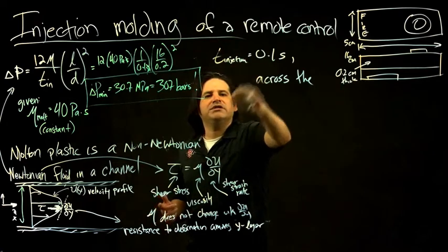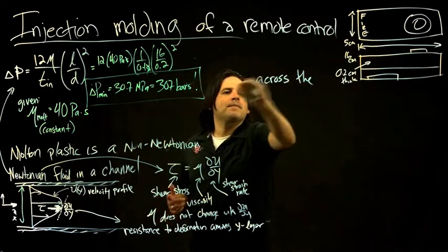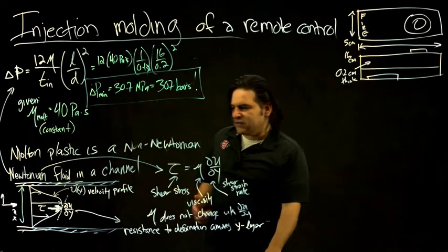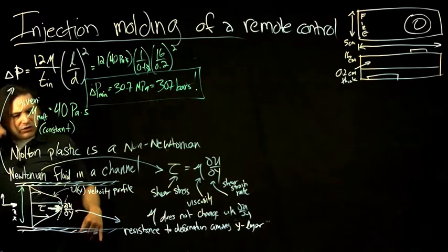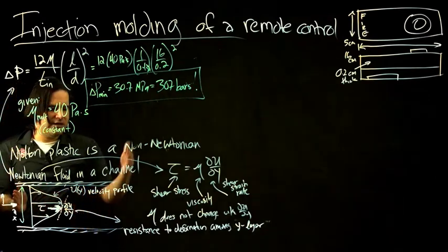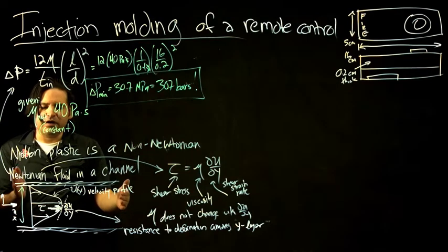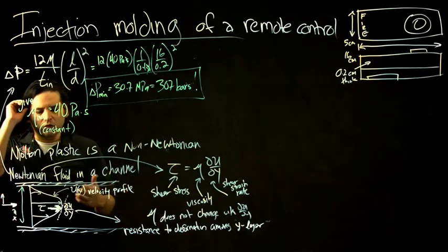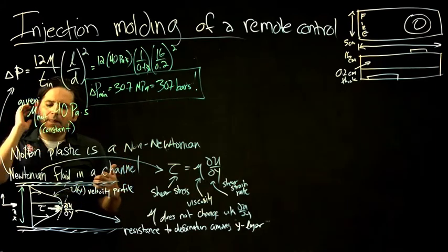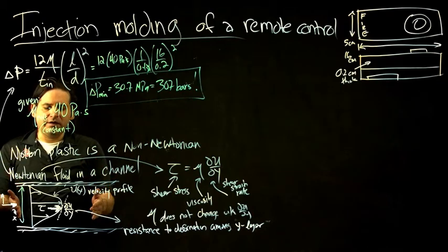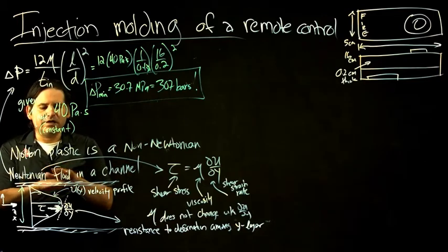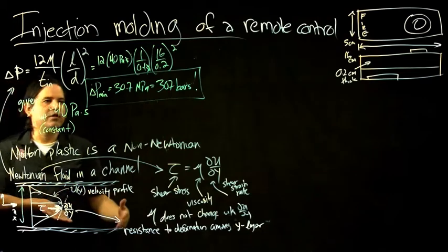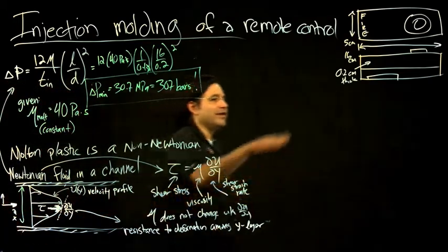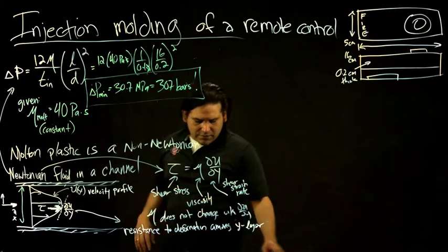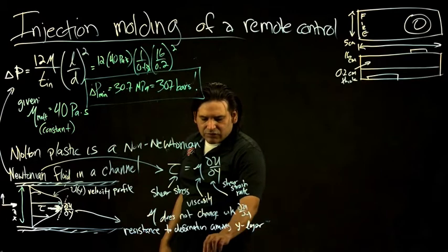So with this equation, this classical Newtonian solution is saying that you're using a pressure difference between this end and that end to drive the mass, to provide a net force from this direction to that direction, which will move the flow to the right. And it's using that pressure drop, and the only thing you're overcoming here is viscosity, friction in a way, the friction among the layers. That's the force you overcome to go from here to there. So that's what we're applying here. But there's more to this shape than that.